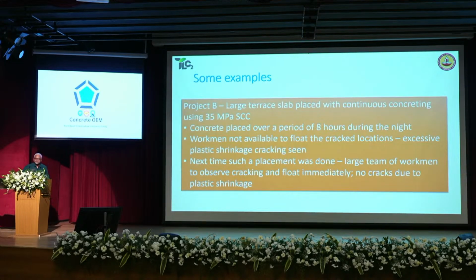In the second project, which was actually a building right inside IIT Madras, there was a large terrace slab which was placed with continuous concreting with 35 megapascal SCC, right? At the previous floor levels, the concrete was placed over a period of 8 hours during the night. Now, we heard from Professor Gettu about plastic shrinkage cracking. The important thing obviously is to ensure that you don't allow the cracks to develop when they start developing, so that workmen have to be there on the site. In case early curing is not done, people have to be there on the site to see where cracks are appearing, use a wooden float, rub it. Very simple way to actually ensure that the cracks go away in the beginning.